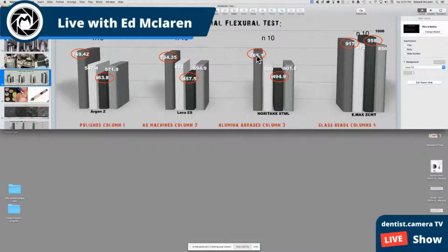Let me give you another little reference here for just a second. So when we typically test things, companies, they're going to want the highest number possible, correct? That hopefully done ethically. So usually when you see people say 700 megapascals, 800 megapascals, they've done it on a perfectly polished sample, so smooth you can ice skate on it. That's going to give you the highest numbers. So here's what we did. I said, well, great, that's nice to know. This is theoretical strength. I want to know the practical strength, the applied clinical strength. And what's that design going to look like?